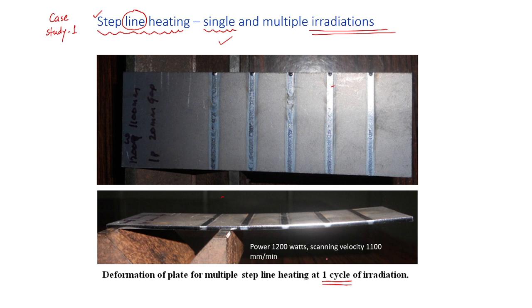So one cycle of irradiation with a power of around 1200 watts and a scanning velocity of about 1100 mm per minute. When we apply these process parameters, you can notice that there is a certain non-linear deformation of the workpart. In this manner there was a bend, but that bend was in a non-linear fashion. Now let us increase the number of irradiations and see what happens.